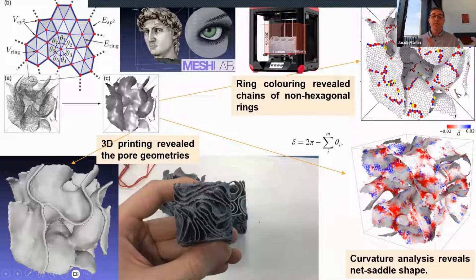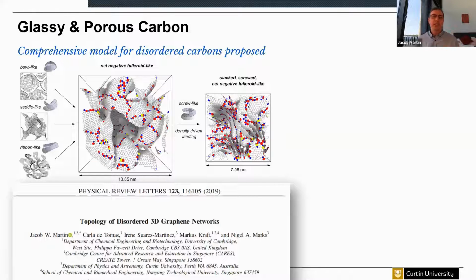And by doing this curvature analysis, we could analyze many of these self-assembled structures. And we found that they all contained a net saddle shape or a net negative Gaussian curvature. And this was quite a hard problem to solve. We'd previously tried just to count the number of non-hexagonal rings, but actually this is a real edge here. And you can see that there's a whole bunch of non-hexagonal rings that are clustering at the edge. So they don't contribute to the curvature at all. So actually counting the number of non-hexagonal rings was a red herring, and doing this curvature analysis on a mesh proved to be much more successful. And so this allowed us to put together a comprehensive model for disordered carbons, all the way from the glassy carbons, the non-porous carbons, which are these here, through to the porous carbons.